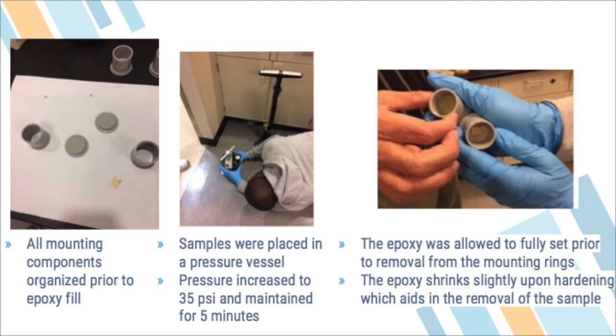The mounting rings, now containing the metal sample and liquid epoxy, were quickly moved to a pressure vessel. The vessel was sealed and the pressure increased to 35 psi by way of a high-tech, uncalibrated, manual bicycle tire pump. The pressure was monitored and adjusted as needed for the entire 5 minutes the sample was in the chamber. This increased pressure environment helped to minimize the size of the air bubbles in the Lecoset. Smaller bubbles helped to make polishing more even and provide better image quality of the polished samples under the microscope.